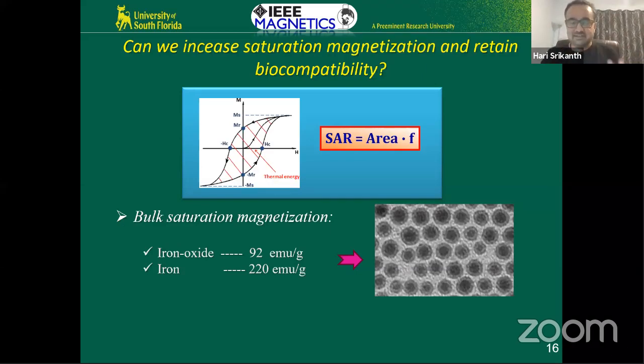Because the cancer cell will see only the iron oxide of the body. Humans will only see the iron oxide, and it will assume that it's biocompatible. But inside, you can have iron, which is completely encapsulated. So using a core shell method, it is possible to get higher saturation magnetization than just these solid spherical or solid iron oxide nanoparticles. So this is the first attempt we did. We got beautiful core shell particles. This is a TEM image of iron core, iron oxide nanoparticles.